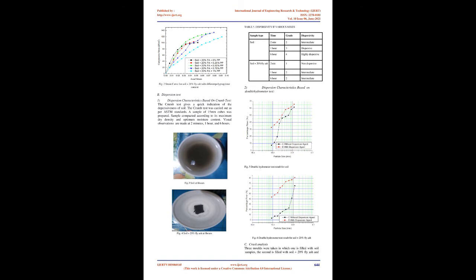2. Effect of polypropylene. The optimum content of fly ash was found as 20%. Take a sample of soil plus 20% fly ash and add different percentages of polypropylene. Strength test was conducted and the optimum percentage of polypropylene was found. Table 4. Variation of UCC on different polypropylene content. PP fiber content, UCS in kN/m2: 0%, 0.25%, 0.50%, 0.75%, 1.00%: 100.3, 103.26, 130.08, 132.9, 119.12.